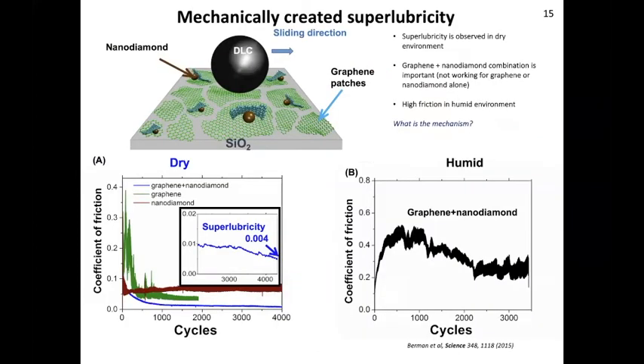With that, when we started testing it, the whole idea of mixing nanodiamond and graphene together came about because when we first tried to test just graphene, our friction was pretty high. When we tried to test just nanodiamonds, the friction was even higher. But combining these two together is what led us to this desirable regime of superlubricity, when our friction fell below 0.01. We actually measured around 0.004. Measuring anything lower was complicated because of problems with the accuracy of the machines. None of the tribometers can give you absolute zero measurements, so you will always have some error in the measurements.